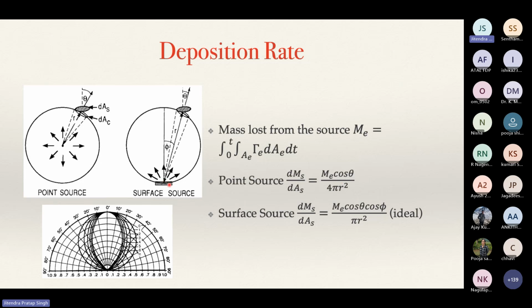But if I'm using an extended source, or sometimes we call it a surface source, then we have to incorporate the azimuth angle also, because you can think of this surface source as the integration of multiple point sources. If I think about the material getting deposited here, there is another point from which material will arrive, and it will have some angle with respect to the surface normal. So there is another azimuth angle which will also come into the picture, and that we say is the cos phi dependence. For an extended source, and practically all sources are extended sources, we have a cos phi dependence here. So depending on the point source and the extended source, your deposition rate can differ.